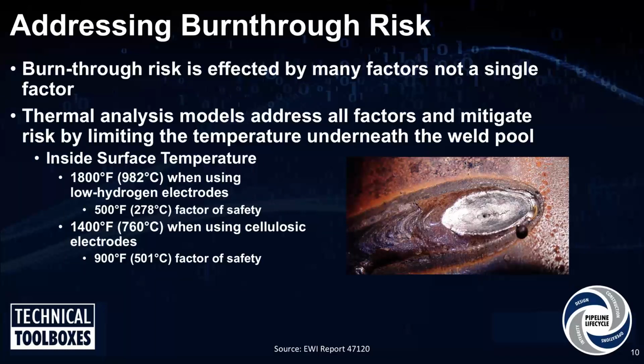So how have companies historically dealt with burn-through risk? Well, one of the more common approaches that companies use is they limit the wall thickness that a welder can weld on. Your typical wall thicknesses are about 188 wall. Some people use 156 wall. But again, wall thickness is just one of the three factors I just talked about.